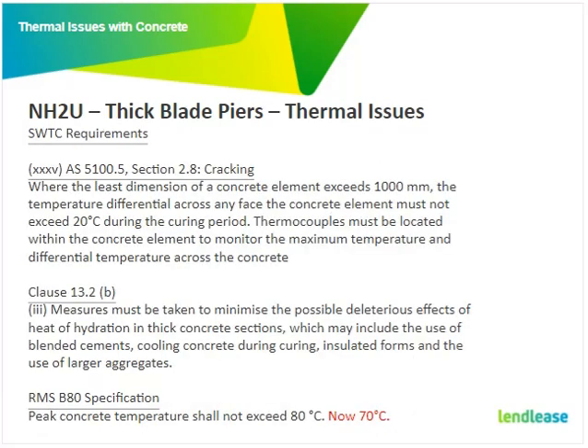These were the requirements: that differential temperature across any face must not exceed 20 degrees. We have to insert thermocouplers to monitor. The other requirements are that measures must be taken for the heat of hydration: using blended cements, cooling concrete during curing, insulated forms, and the use of large aggregates. Now we did all that, you still don't achieve the peak temperatures, but I'll continue on that. So on this project, the peak temperature limit was still 80 degrees, and as I said before, it's been reduced to 70. In this case, I think it'd be almost impossible to achieve.